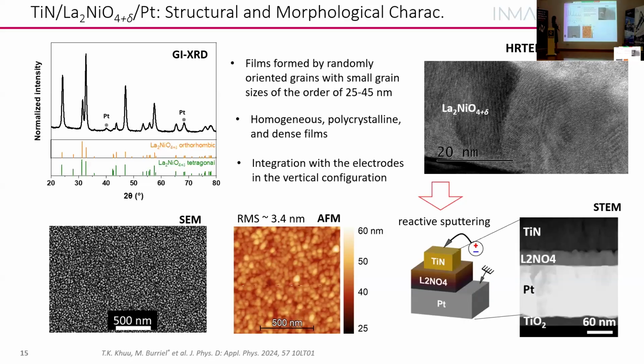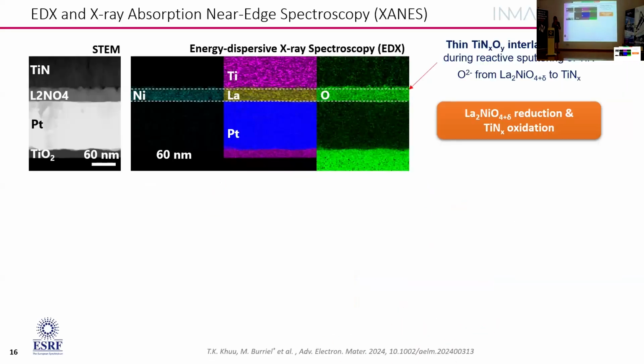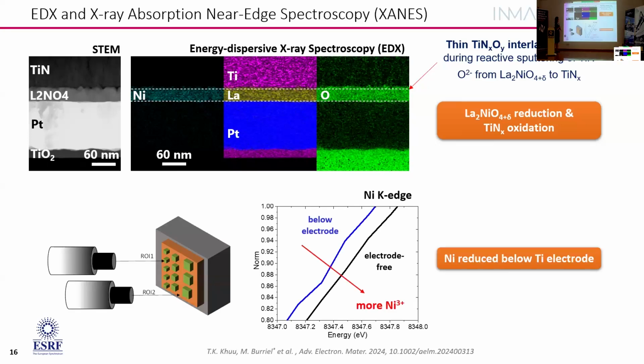Then we deposit titanium nitride in the clean room by reactive sputtering with some masks to obtain the devices here. Then we characterize these devices in depth, and we already observed that just because of the titanium nitride deposition, we had some oxygen migration to that interface. So lanthanum nickelate gets reduced and titanium nitride gets oxidized. And this is very important for the switching behavior of our devices.